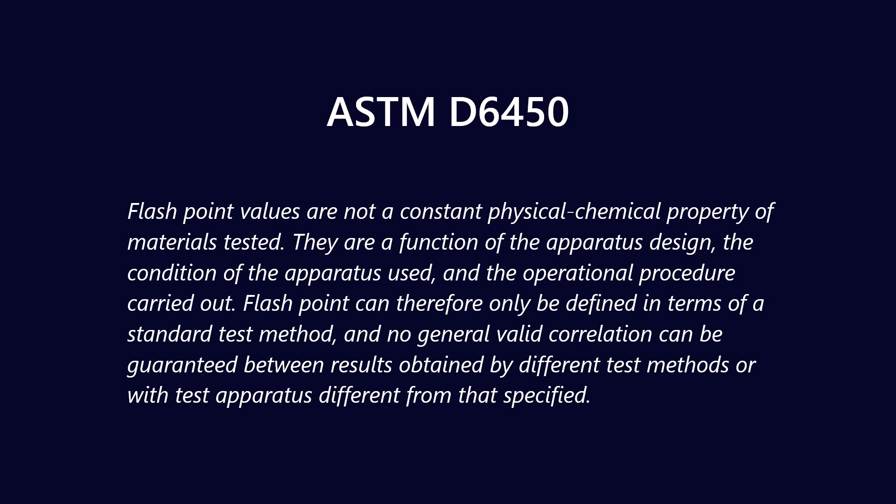One important thing to note is that flashpoint is not really a physical property of the lubricant in the way that viscosity is. Viscosity is a known quantity with methods to measure the true value. Flashpoint, however, is completely dependent on the test method used — there is no single 'real' flashpoint for a lubricant. That's why D92, D93, and D6450 don't correlate well with each other.